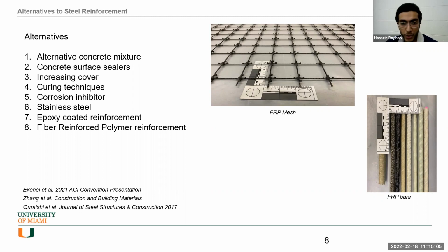To this end, to make applications such as horizontal constructions, as I mentioned before, the slab-on-grades, more durable and sustainable, the use of non-metallic fiber reinforced polymer, which we call FRP, rebars and meshes as the secondary reinforcement can successfully address the shrinkage cracking challenges. The FRP rebars are a suitable alternative to steel, to epoxy coated steel, stainless steel, in different applications where your concern is the durability, or you need magnetic transparency because they're fibers, right? Or you need ease of demolition for temporary structures. You have some structures that are not permanent. You want to destroy them very soon, and you need something that you can destroy more easily.